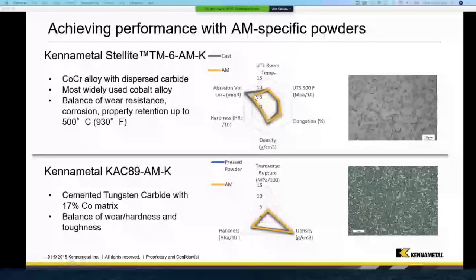With our Kennametal tungsten carbides, we have KAC89-AM-K. This is a cemented tungsten carbide that has a 17% cobalt matrix. Again, a good balance of wear and hardness that you would expect for tungsten carbide, but with the 17% matrix, it's a tougher material. And again, it directly overlays with what we see with respect to the three primary properties that are always measured, which are transverse rupture strength, density, and hardness.